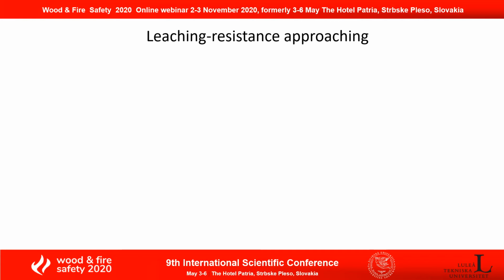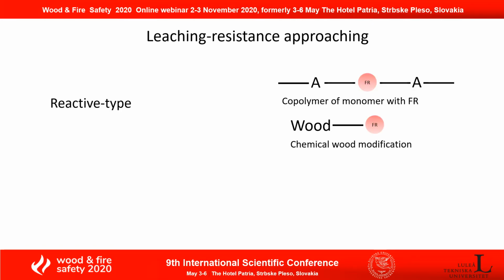There are two approaches to achieve this leaching resistance, and first of all is the so-called reactive type. You take your fire retardant additives and react them with other monomers to let them become a part of the polymer chain, and by doing that, you could stabilize your fire retardants in the polymer chain. Or you take your additives to react with the wood matrix to create a stable covalent bond.